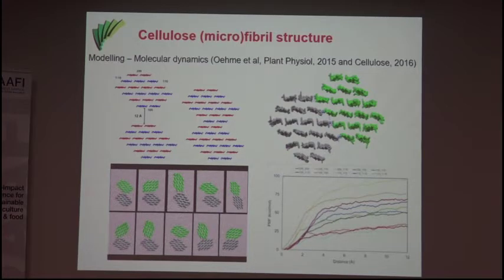But the cell wall, the cellulose synthesis occurs pretty quickly. It's that cellulose synthesis rosette moves at 300 nanometers per minute. So it's pretty fast. And so we think that it's probably more a kinetically trapped structure where there isn't the chance for the thermodynamics to come into play. But this remains to be examined experimentally because we don't have the tools yet to do that.